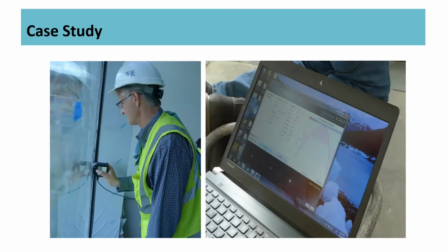So we have been measuring the thickness of the glass and the RCSS, the residual compressive surface stress, using an optical device. In this case, it's a SCALP, and the SCALP plugs in through USB to a computer, and then it's able to perform the measurement, and we get a nice fancy drawing here of that stress profile through the thickness of the glass. Okay, so that's where our picture came from previously, from this device.